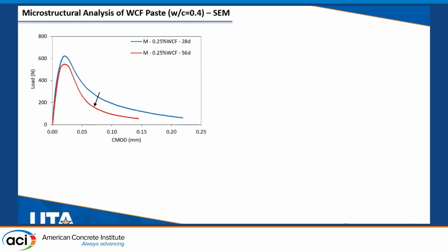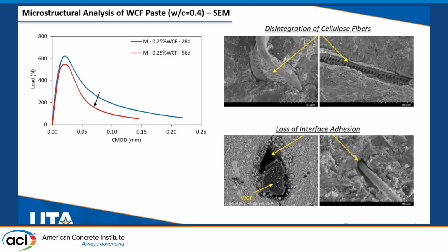Extending our mechanical testing to 56 days, we noticed a reduction in the mechanical properties, such that the load-CMOD curve of the WCF mortar at 56 days falls below the load-CMOD curve of the same mix at 28 days. Using scanning electron microscopy, I noticed that these fibers have undergone disintegration. Also, after they release the absorbed water, they shrunk, and a loss in the interfacial adhesion is observed. Both of these phenomena can explain the reductions in the mechanical properties and must be addressed to preserve the long-term mechanical properties and overall performance of the composites.